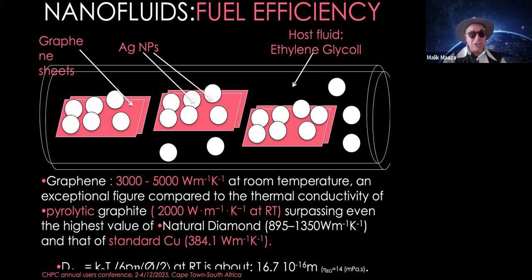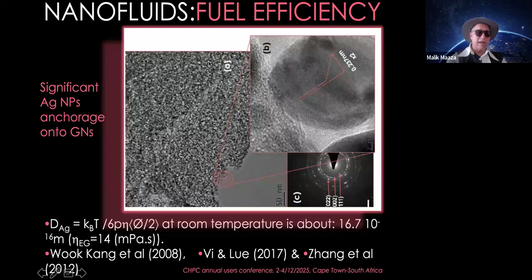And that sheet of graphite has an extremely elevated thermoconductivity, higher than the thermoconductivity of a diamond. And if you decorate it with silver, which in effect is the metal with the highest thermoconductivity of any metal. So if machine learning, density functional theory and data mining had not allowed us to go that route, we would not have thought about it. And here it is. Here on the first page are graphene sheets. Here are silver nanoparticles. Boom. And here is graphene covered by silver nanoparticles.